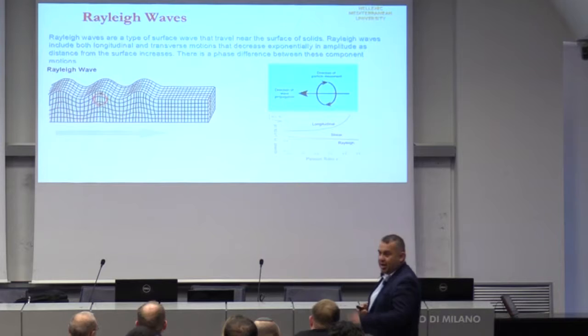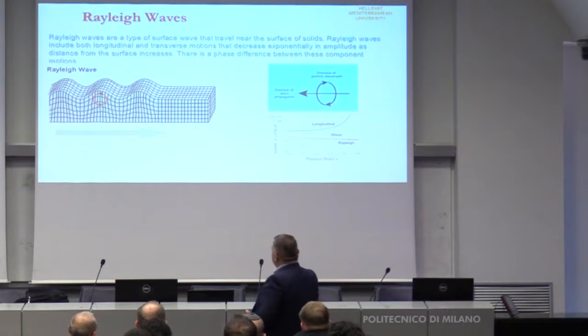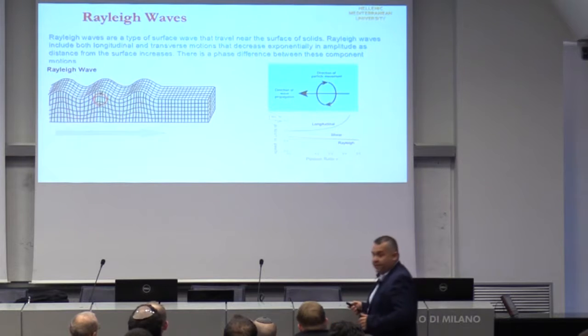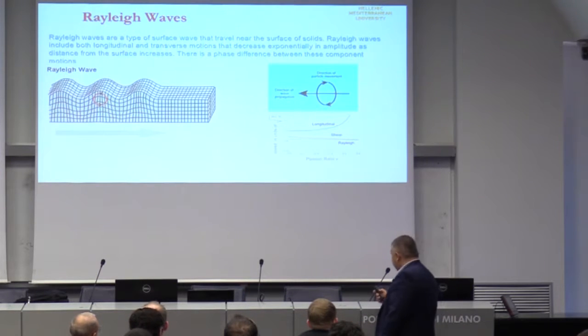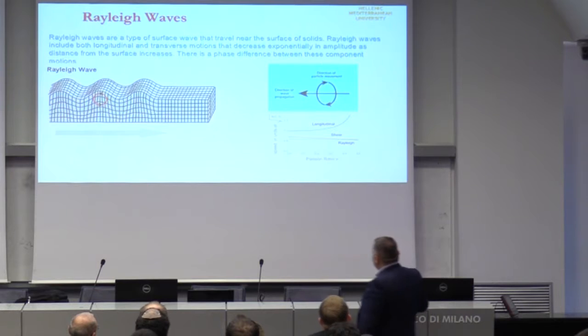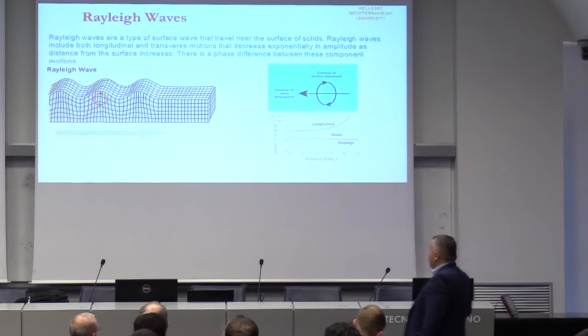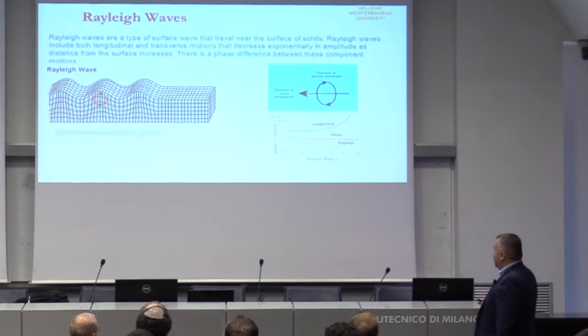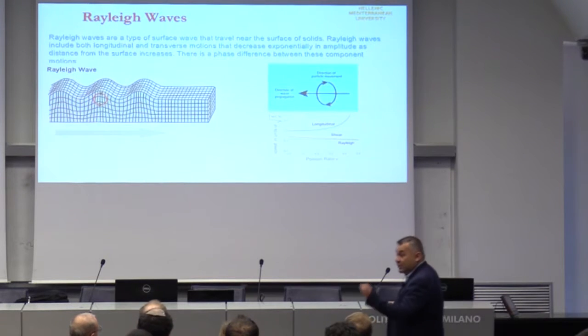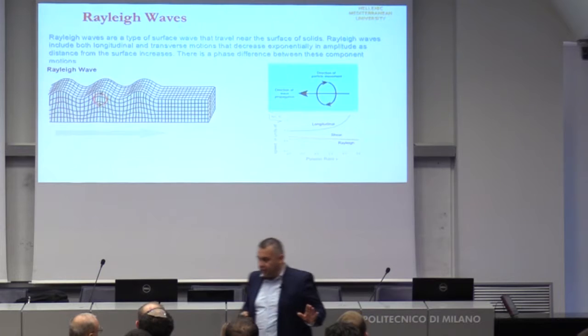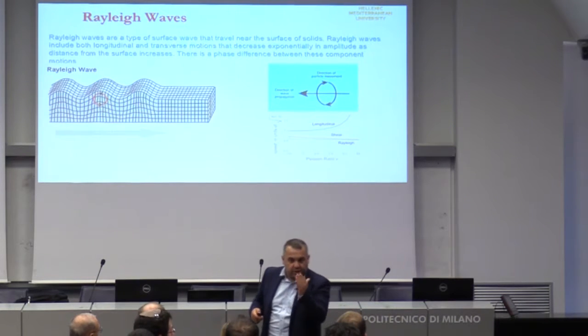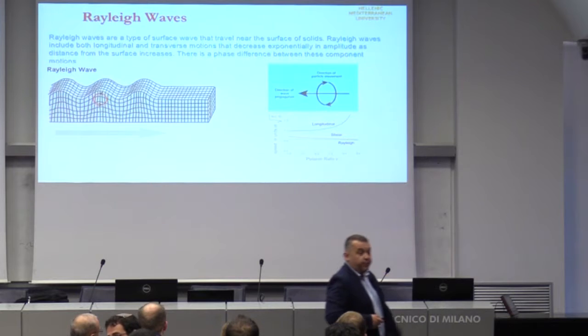It's the so-called Rayleigh type waves, where in a Rayleigh wave, like sea waves for example, we have this kind of wave, and each point inside near the surface is doing a cycle, an elliptical motion. This is the direction of particle movement. And if you see the speed, the Rayleigh speed, depending on the Poisson ratio, is nearly constant, completely different from the longitudinal waves, where there is an increase of speed as there is an increase of Poisson ratio.